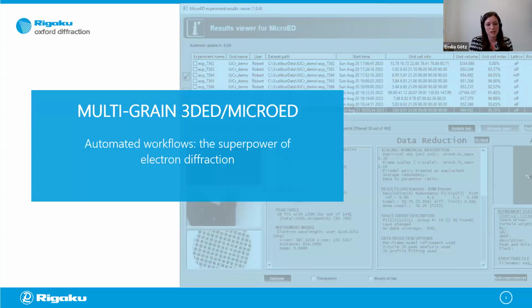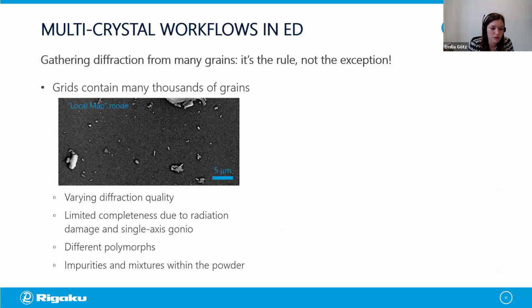Because the key difference of electron diffraction with respect to X-ray diffraction is the importance of multi-crystal workflows. And the reason for this is quite obvious if you look at the specimen for electron diffraction, which is comprised of not one, but thousands of crystals, which are deposited on the sample grid. And here we can just see a tiny section of the sample grid where we already have dozens of crystals. And those usually vary wildly in quality of diffraction to get out of them.